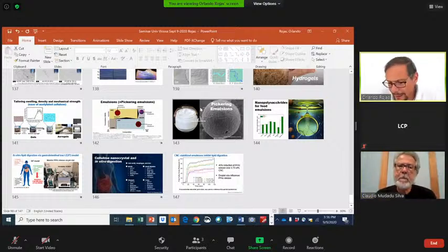So the nanocellulose from bacteria, we usually call bacterial nanocellulose. The bacterial cellulose that is produced by biological microorganisms is a very interesting material. So the short answer is that the cellulose that is produced by bacteria is pure, in contrast with the nanocellulose that is produced from plants. No matter what you do with the starting fiber, there is always going to be residual hemicellulose and residual lignin in the final nanofibrillar cellulose. But in the case of bacterial cellulose, of course, most of you know, it is pure cellulose. And the second thing is a high molecular weight, a higher degree of polymerization.